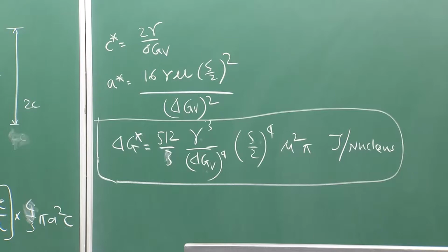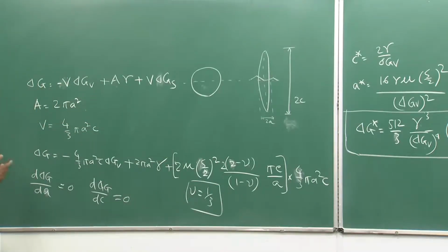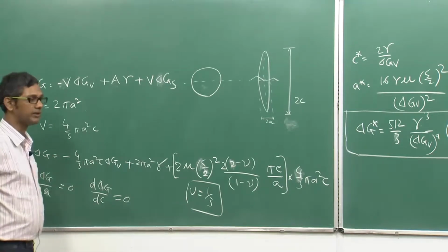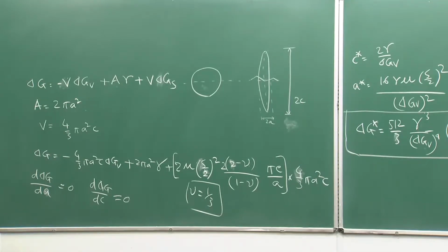Second important part is that this free energy, if you look at this, is total free energy both for nucleation and growth. And as growth is very fast, we have only considered this as homogeneous nucleation here. We have not considered the heterogeneous part. It can happen anywhere inside these grains, or there is no preferential treatment of the grain boundaries as a nucleation site for martensites.